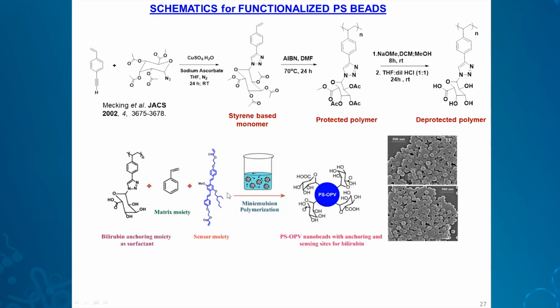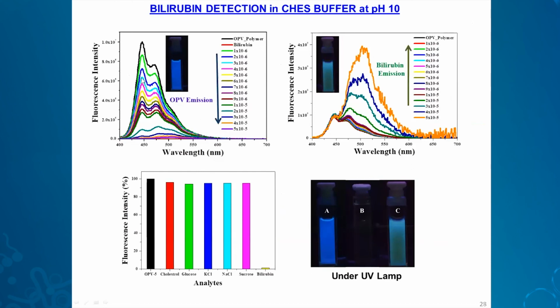And this is the miniemulsion polymerization system, and we get these beautiful beads, almost monodisperse in particle size, which have blue fluorescence and are decorated with glucuronic acid on the surface. So these are the same quenching studies, the quenching of the polymer fluorescence and increasing the bilirubin emission. Again, the sensitivity also could be studied. And here you can see that the visual detection is much better than the polyfluorene case. This is the blue polyfluorene, and this is in presence of bilirubin. It is a cyan color.